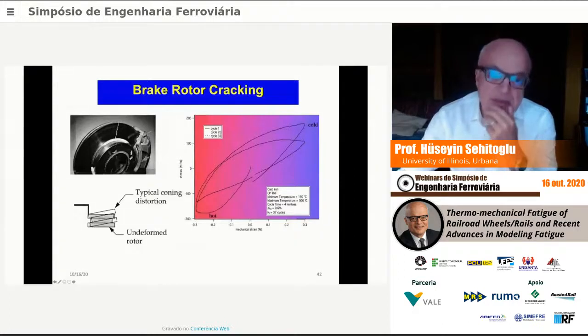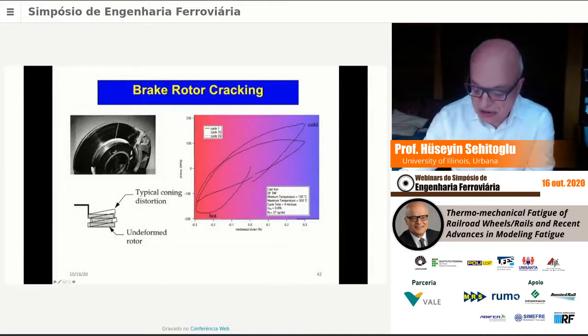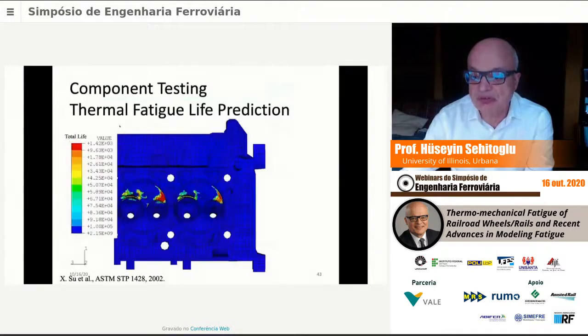I mentioned some other examples of thermomechanical fatigue. This is the brake rotor cracking, and this is cast iron. And again, you heat, cool, heat. So this is obviously out of phase loading, and the range of strain is 0.6%, and we failed in 37 cycles. So this is a different material, but obviously there's cracking that initiates from that.